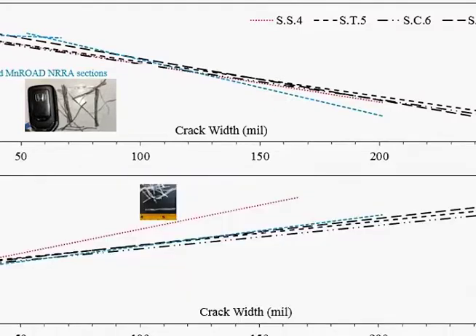Okay, and then in terms of the load transfer efficiency, we saw that with respect to crack width, the fiber that we used didn't give too much of a difference, but that's the important thing. Sometimes load transfer efficiency can be misleading. Here you see one particular type of fiber, the straight synthetic one, did give more displacement. Even though load transfer efficiency was good, that means if we apply the load, both slabs go down, load transfer efficiency is good, but they go down more. That's not good, right? So we'll have to be really selective and choose good fibers.